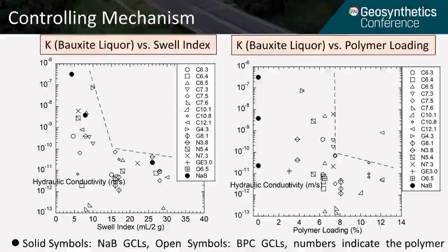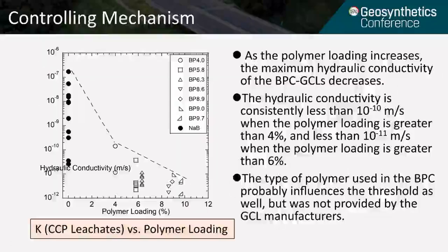Because our understanding is polymer is playing a big role in this game. So when we compare the hydraulic conductivity with polymer loading, we see when you have sufficient polymer loading, it will better maintain the hydraulic conductivity. Especially for the bauxite liquor, if the polymer loading is higher than 8.1, you will have hydraulic conductivity generally lower than 3 times 10 to minus 11.